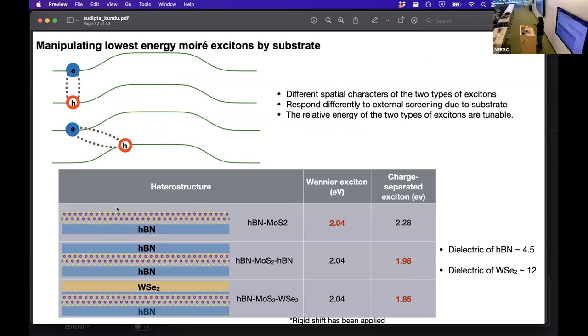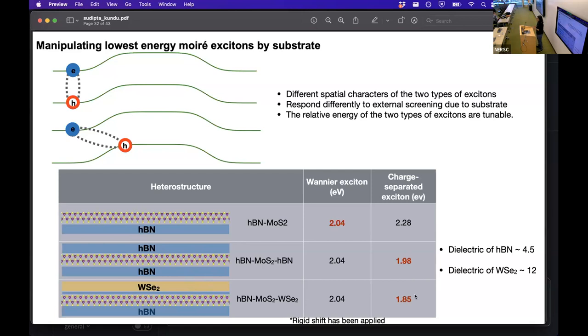In our heterostructure with TMD on top of an hBN stack, the intralayer-type exciton is the lowest energy exciton and the charge-separated exciton is higher in energy by 240 meV. But if we encapsulate the TMD with hBN on both sides, the charge-separated exciton becomes the lowest energy exciton. If we further replace the top hBN by a higher dielectric material such as WSe₂, the charge-separated exciton further lowers its energy. So by changing the dielectric environment we can tune between these two types of exciton.